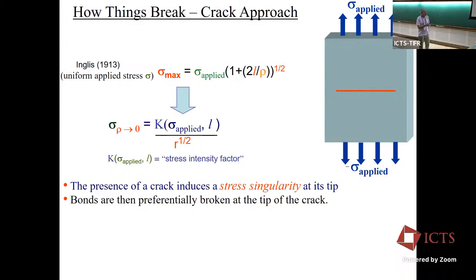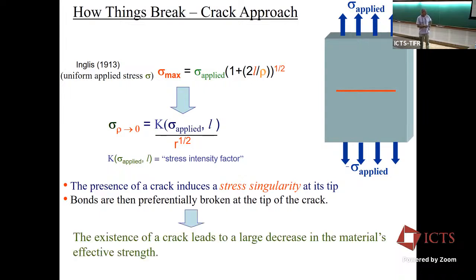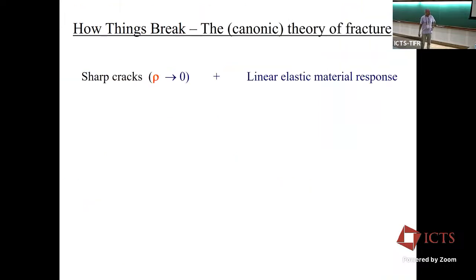So what cracks do is they focus the elastic energy that's being applied at the boundaries into this singularity. So bonds now are not broken uniformly, but in a very efficient manner, kind of like dominoes. So this stress singularity will break the material bond after bond right at the tip. And it makes materials much weaker. So, okay, the bottom line is the existence of a crack leads to a large decrease in a material's effective strength.